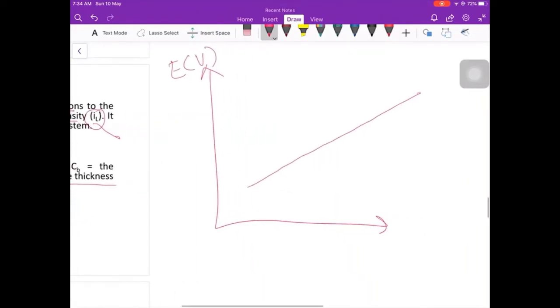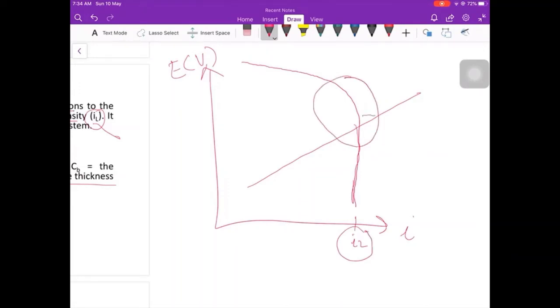The anodic is just straightforward, going upward. But for the cathodic reaction, which is the hydrogen evolution, for example, at high potential it has activation, and slowly it will go flat here. So this is IL, the maximum it can reduce. This is called limiting current density. This area is the cathodic where concentration polarization controls. If there is a slope here, this is activation polarization. But when it starts to bend, in this area, this is concentration control. This is the limit for the reduction process.